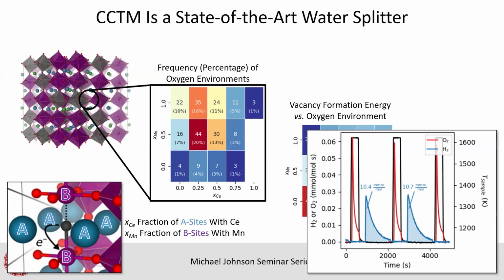And in fact, if you go and do an experiment here, the black line right there is temperature that's being imposed on the sample. Every once in a while, there's a big spike, basically like a big rectangle that comes up. That's a big heating cycle. When you heat it at around, say, 500 seconds, you see a big red peak. That red peak is the oxygen coming off. We can actually measure that.